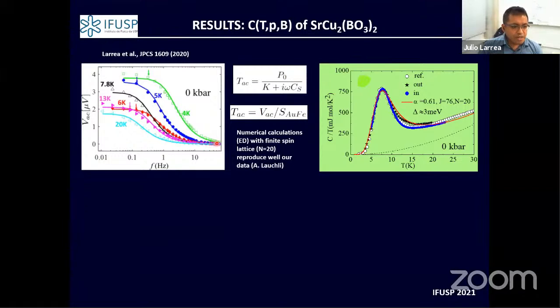What I was showing before is that the experiment follows this model. We have to change the frequency, and we do that at different temperatures, isothermal curves. Just to give an idea, each point you are seeing here takes around 3 or 4 hours of measurement, depending on which frequency you are at. So basically a curve could take at least a day, or sometimes even longer, depending on the frequency.